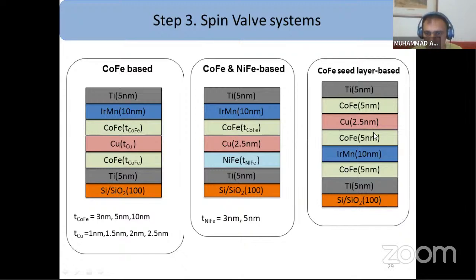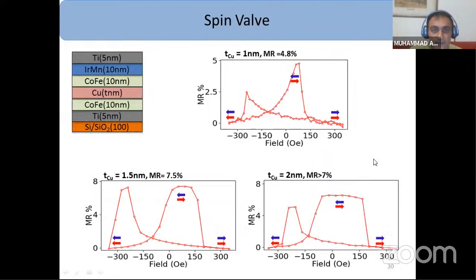The good thing about this sample is that we have got the MR value without annealing the spin valve. We got a GMR without annealing the bottom spin valve. First of all, I have shown this cobalt iron of 10 nanometers. This is a reference layer, and this is the non-magnetic layer. I have varied this.